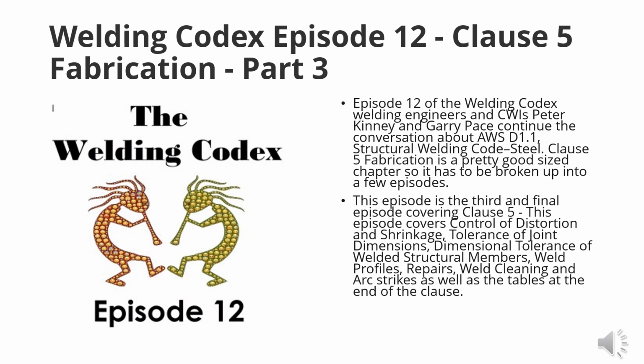So weld tabs, what we're talking about is you have an extra inch or two, you throw a little piece of material that is probably similar to what your base material is, but it gives you a start, so you don't actually start or stop in the weld joint. You've got a little extra time there to get it going, and then you're in the weld joint, and when you're terminating the weld, you go an inch or so after the weld, and then you can come back later on and knock those weld tabs off, clean everything up, and life's good.